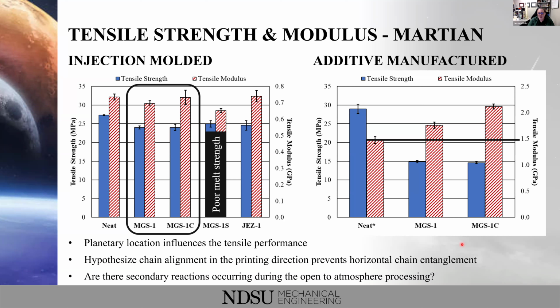My student dug into it a little bit more, and what we really think happened is in the slow process of additive manufacturing, right? When we think about injection molding, it's a really fast injection of the material. It flows very quickly out into the mold. You get some chain alignment of the polymers just because of the flow and how fast it is, but in reality, it's really an isotropic material, with chains going in every different direction. But we believe with additive manufacturing and the way our Terabot X is working, we're getting a lot more chain alignment in the printed part, in the direction of the print. And so we see a much stiffer material from our neat polymer. There's a little bit of work we need to do to figure out what's really happening. We can do some testing by printing in different directions, but we haven't gotten to that work quite yet.